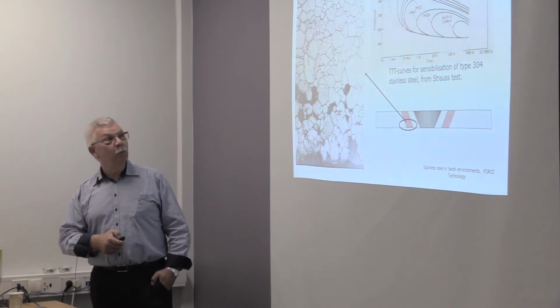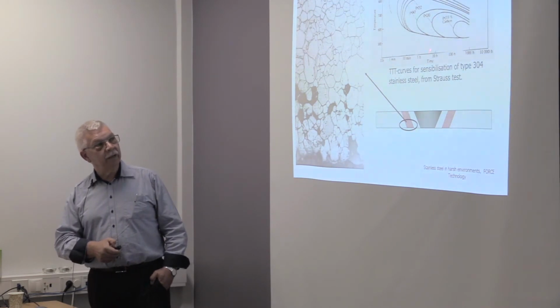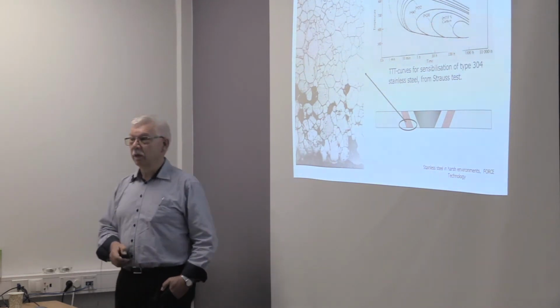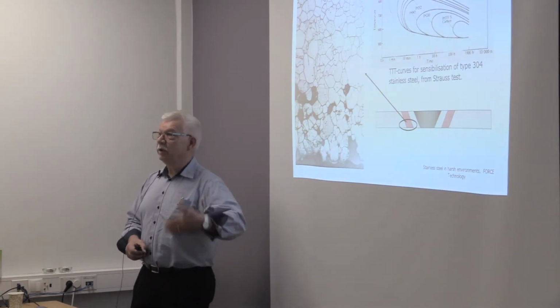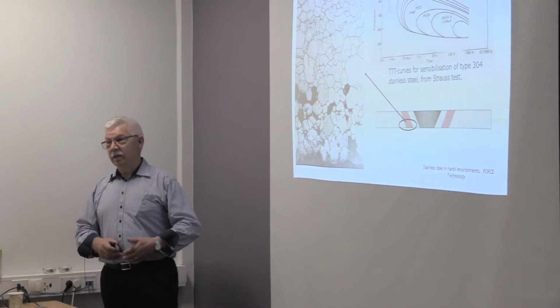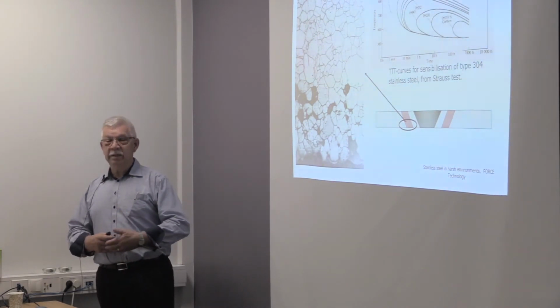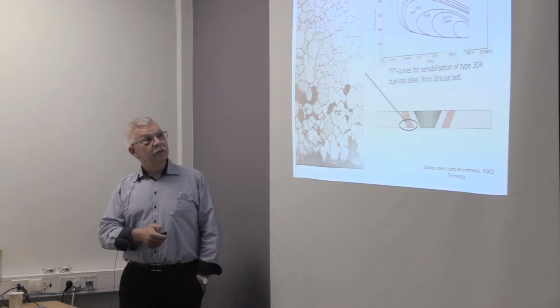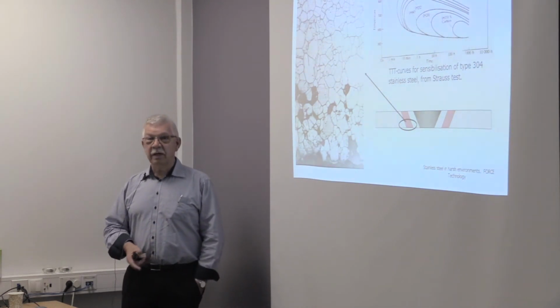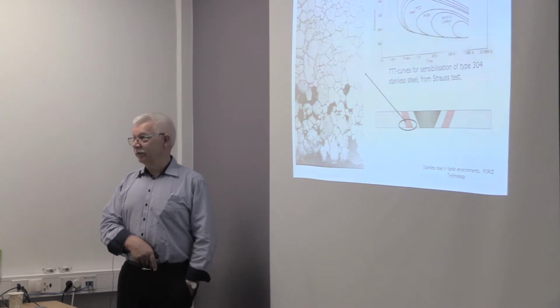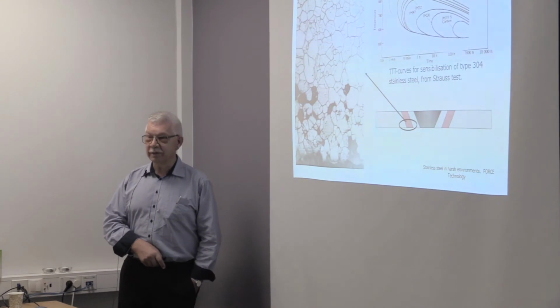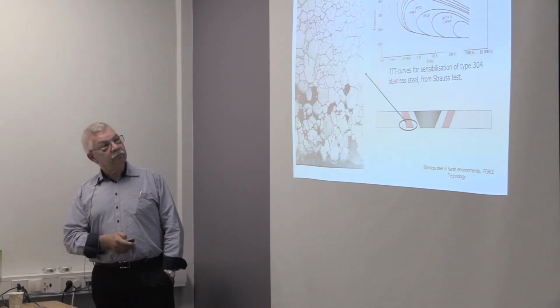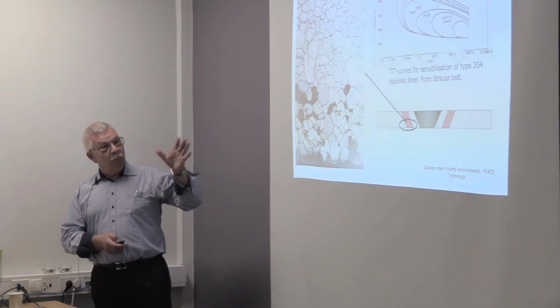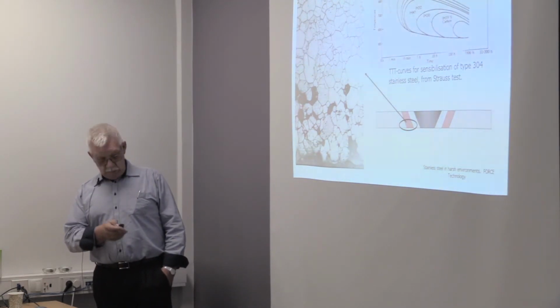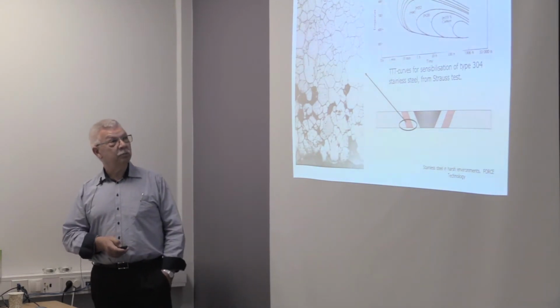If you choose to buy with the L, the limit is 0.030, so that you have like 7-8 hours before you have problems with that. And that's accumulated time. So if you weld, make a defect, grind, weld again, then you might at some point reach these 8 hours. But I think you should go here before you weld any further if you have that problem that it will take you 8 hours to weld this system. So usually materials with low carbon, we don't see this kind of problems.